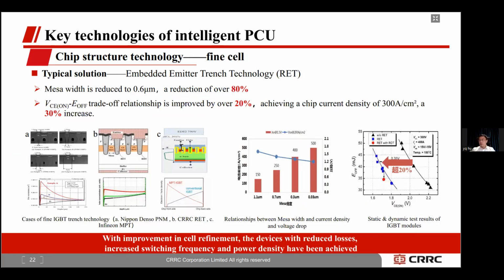With the improvement in cell refinement, devices with reduced loss, increased switching frequency, and higher power density were achieved. A typical solution, embedded emitter trench technology, was used here. The mesa width was reduced to 0.6 micrometer, a reduction of over 80%, and the VCE(sat) minus Eoff trade-off relationship was improved by over 20%, achieving a chip current density of 300 amperes per square centimeter, a 30% increase.